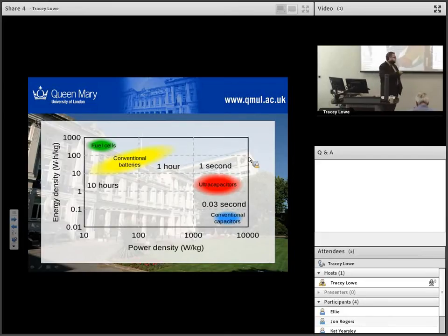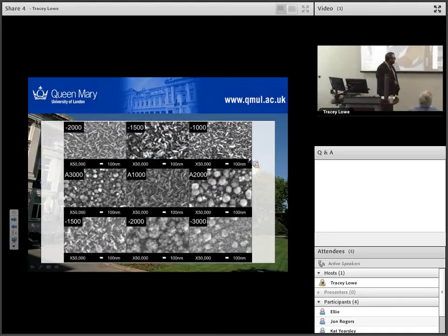So ultracapacitors or supercapacitors have high power density and relatively low discharge time - useful. So we grew a bunch of films, and you can see here... oh, that's not coming out right, is it? This top layer should be plus rather than minus. You can see this on these little metal substrates.